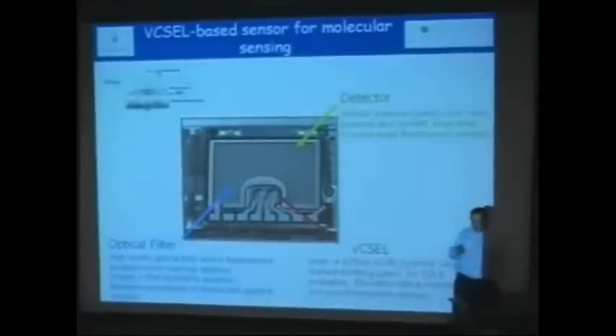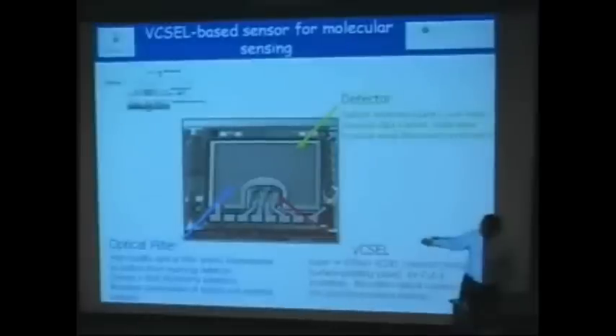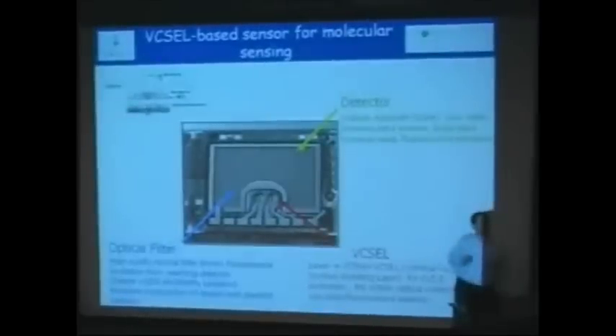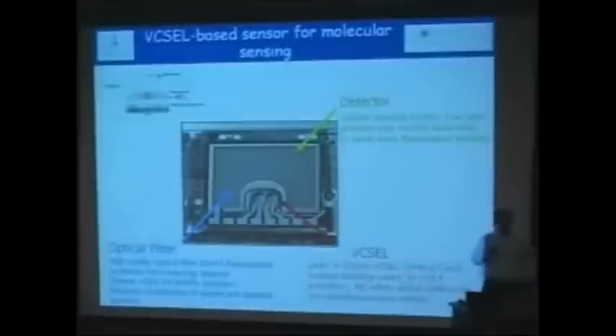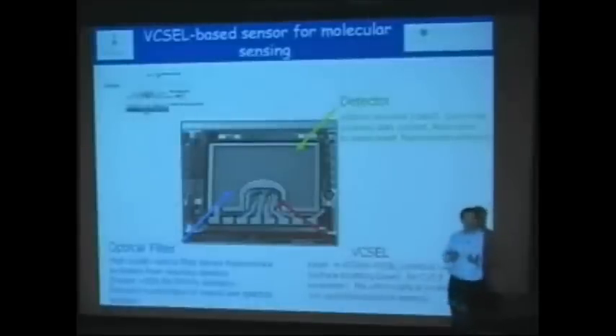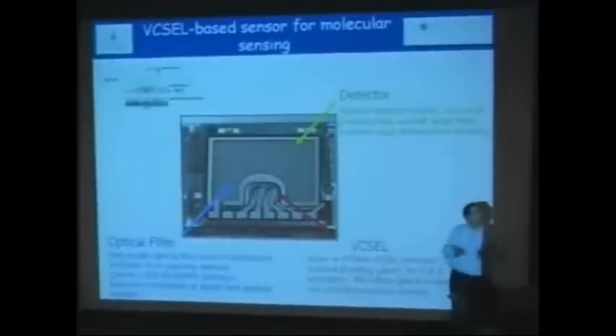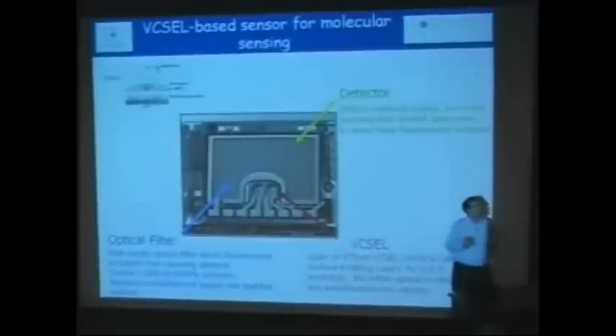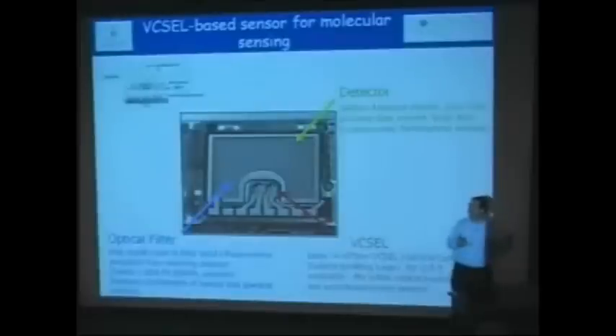The only thing that is left is what's shown here, and you cannot really see it, but there is a 7-micron layer of optical filter just covering all the detector. The purpose of that filter is to block the laser light while allowing fluorescence in. Any fluorescence detector blocks the laser light and allows fluorescence in. Normally, fluorescence is about 5 orders of magnitude lower in intensity as compared with the laser, so it's a real challenge to block. The design was about 10 to the 6th in blocking. With all imperfections, it's not as good, but you have to work very hard to design a filter that absolutely blocks all the laser.